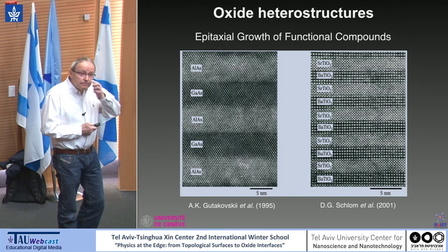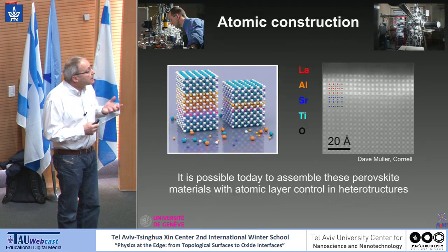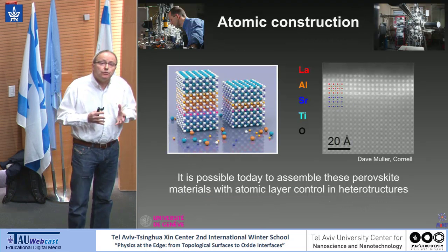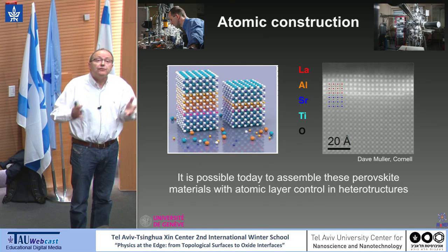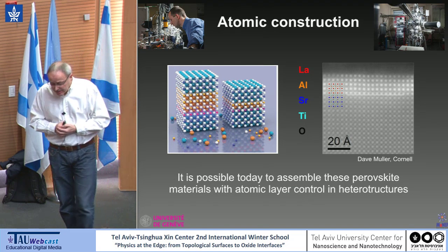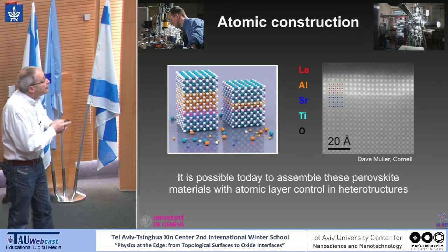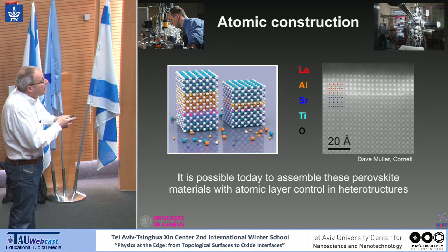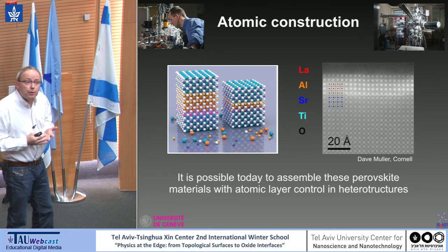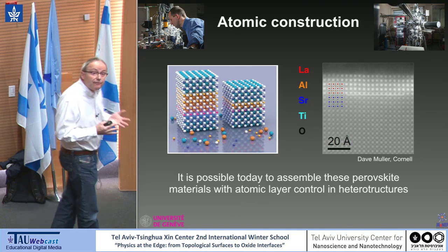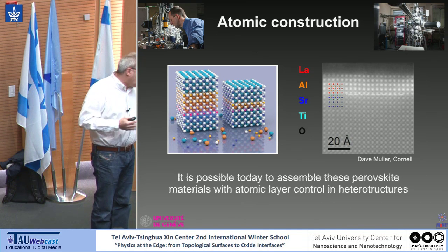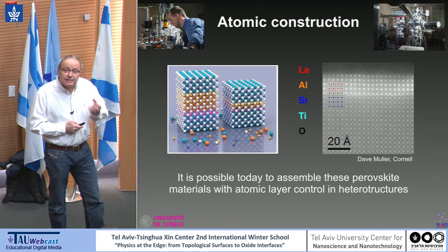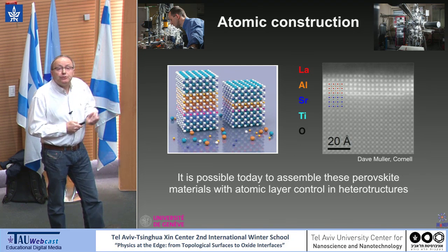Now, I said just before that these materials are quite sensitive to perturbations. You have different states which are close in energy. Now, if you think about an interface, and you see here the interface, an interface is a major perturbation because you've changed half of the neighbors. And so on general grounds, one can imagine that this interface may produce